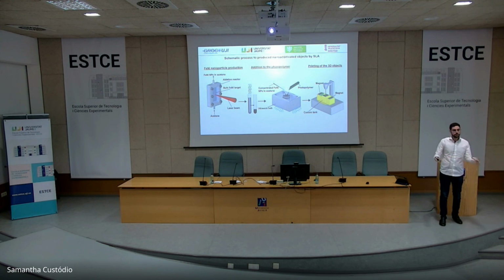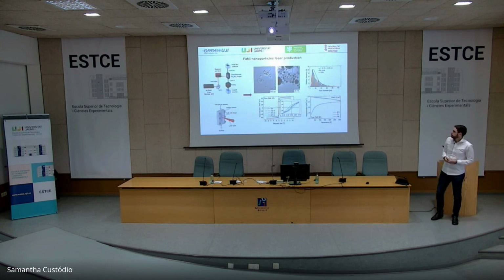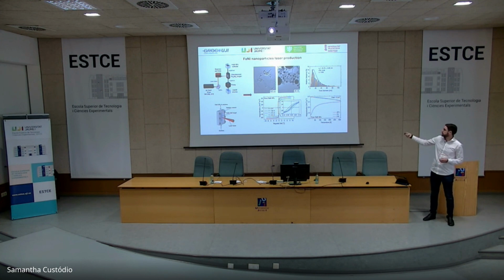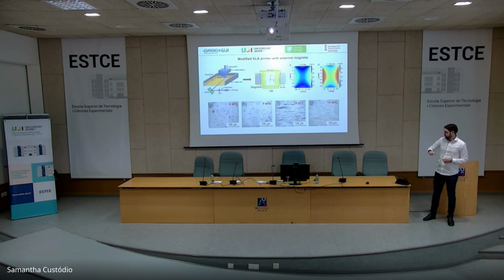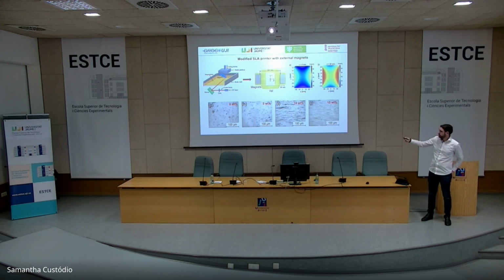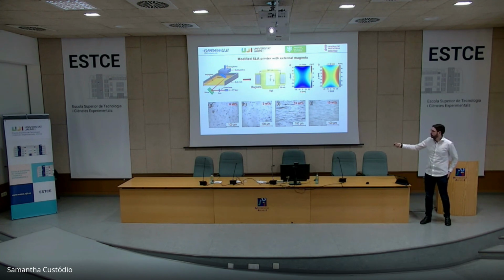If we have just dispersed magnetic nanoparticles, when we print something, we will have some magnetization, we will have some magnetic properties, but not spatially resolved. So they will be just homogeneous. If we can do an orientation of these nanoparticles, well, here you can see the size distribution of the nanoparticles and their magnetic response. But if we do some orientation of these nanoparticles, what we are achieving is basically this situation. When we move from a stronger magnetic field to a less strong one, and also change the concentration of acetone, we can go from a situation where these black spots, which are the iron nickel nanoparticles, or here even larger particles, are more or less homogeneously distributed.